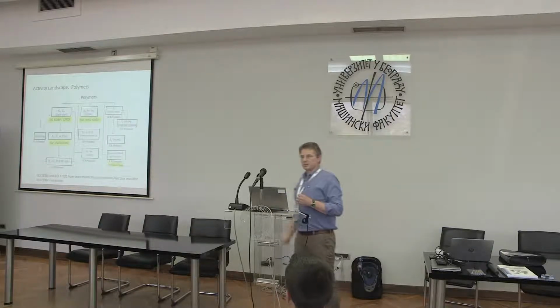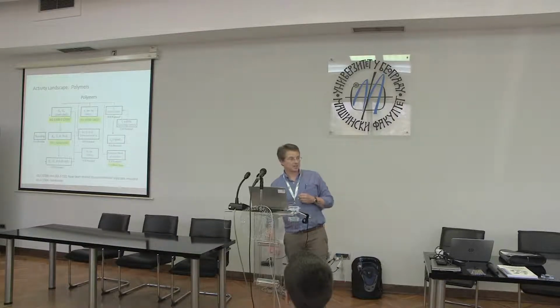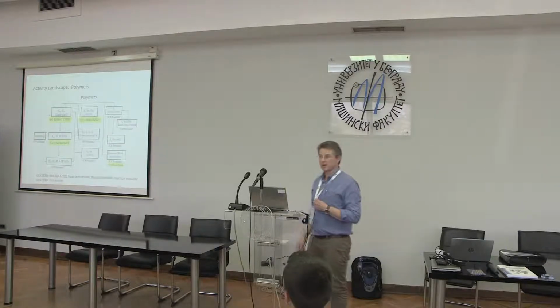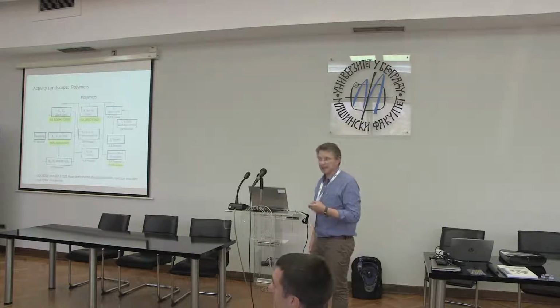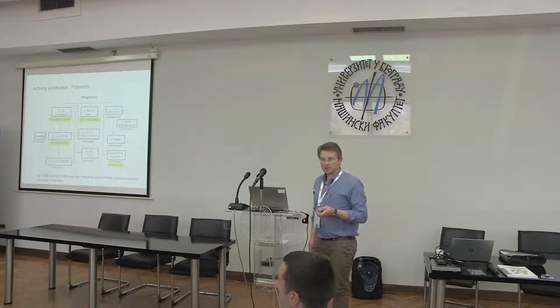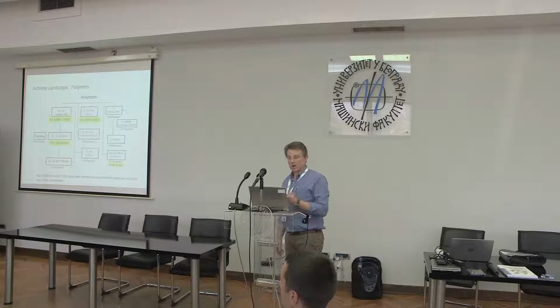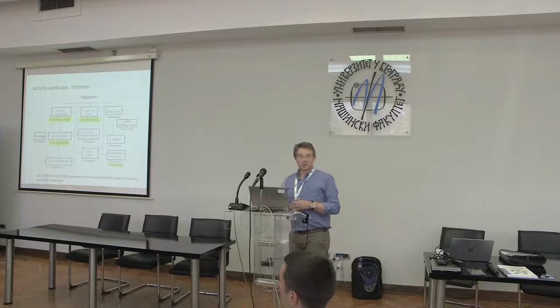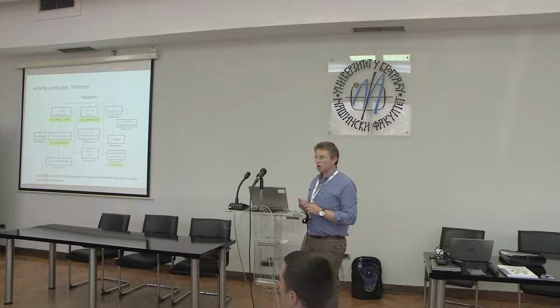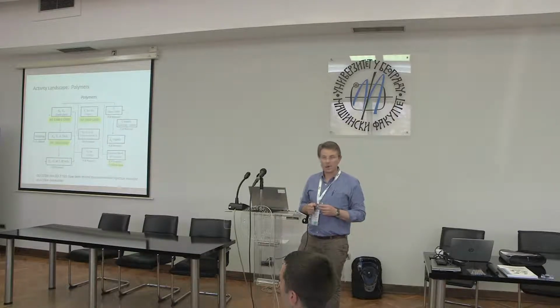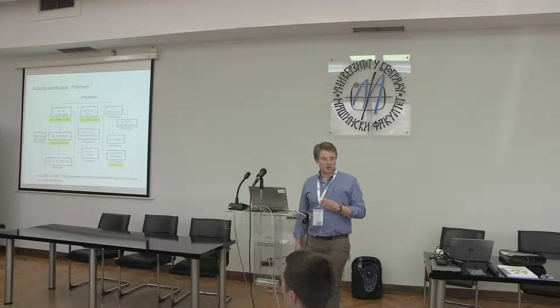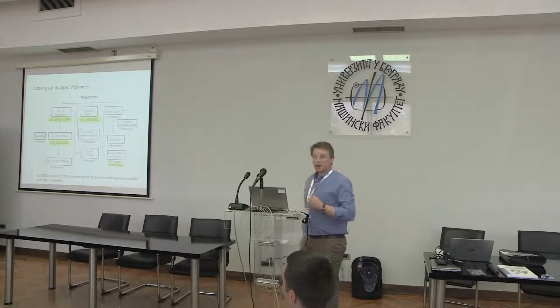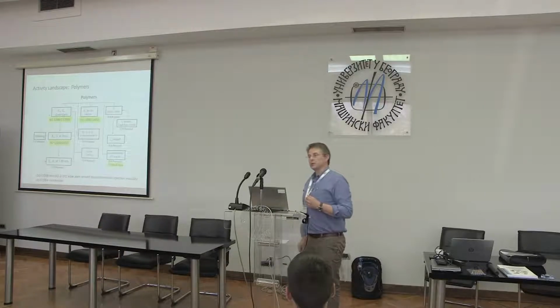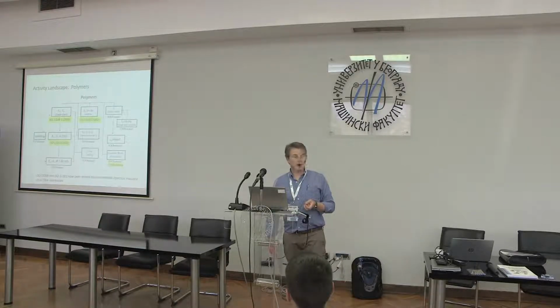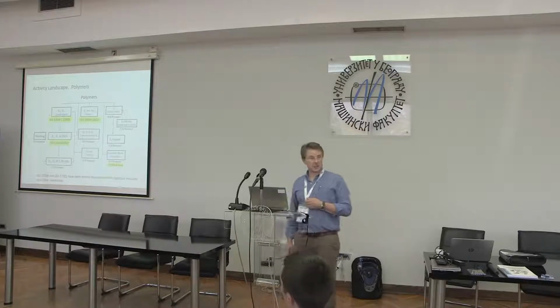Looking down the right-hand side of this column, you see the elastic plastic fracture mechanics area. So this is where the LEFM methods are not holding. We have substantial plasticity and non-linearity, and therefore we need different methods. So the LEFM methods become invalid, and we have a J1C. It's not a standard, it's a protocol, because there have been significant issues with applying the J1C method in polymers. It's been a major work area within TC4, and a great difficulty has been really controlling the amount of crack growth that you can actually achieve in that sort of test.